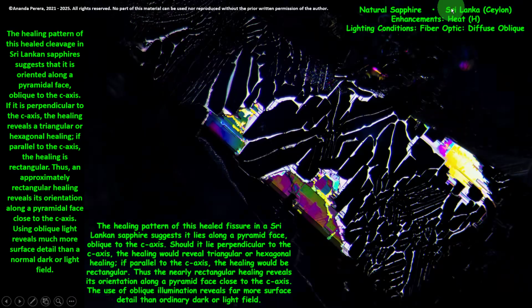Look at this. Sri Lanka sapphire, but it is heated. What are the lighting conditions? Fiber optic, diffuse oblique. Only one lighting condition. Diffuse oblique fiber optic light is used to see this healing pattern. The healing pattern of this healed cleavage in Sri Lankan sapphires suggests that it is oriented along a pyramidal face oblique to the c-axis. We learned this earlier with the natural inclusions.